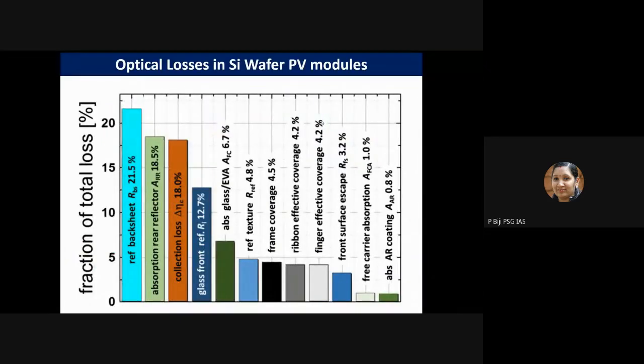So now the most significant loss is the photon loss. If you consider the different contributions of optical losses in the PV module, you can see in this chart that the most significant loss is the photon loss at the back sheet, even after considering the lateral harvesting from the conventional white diffuse back sheet. Therefore, in order to improve the output power of a PV module, it is important to optimize the lateral photon harvesting from these areas also.